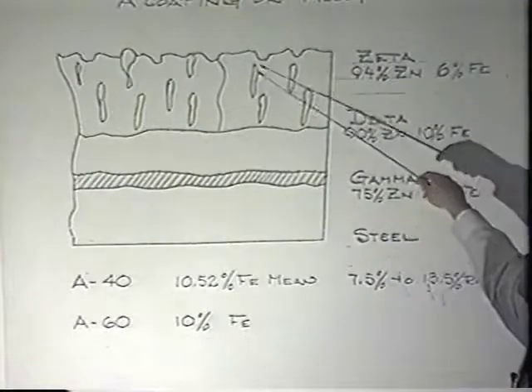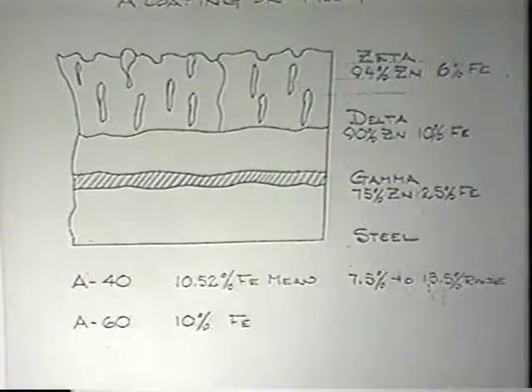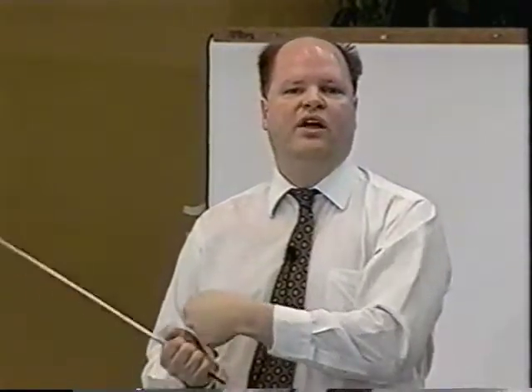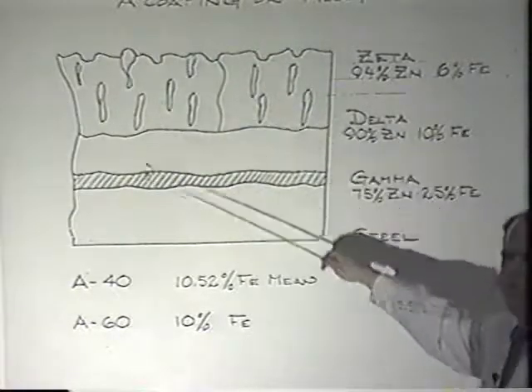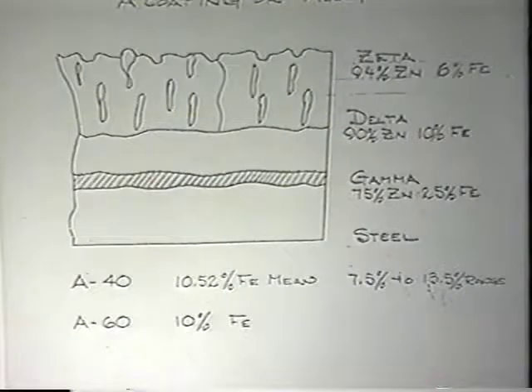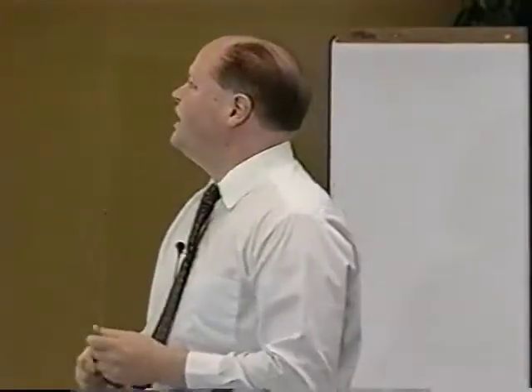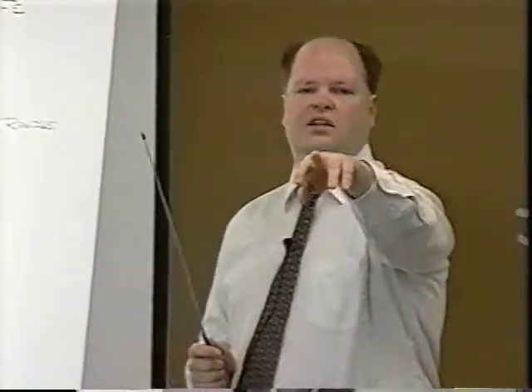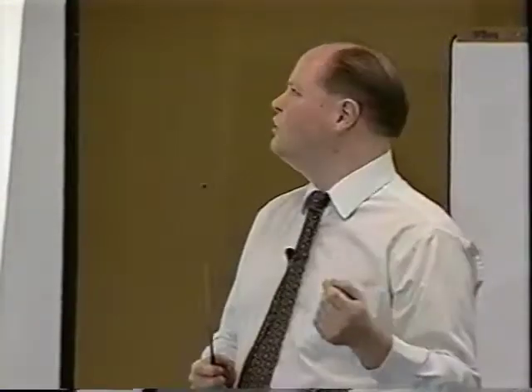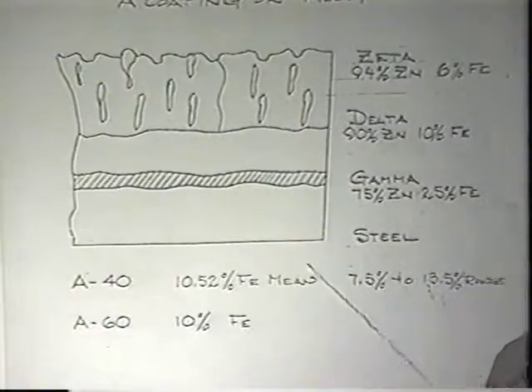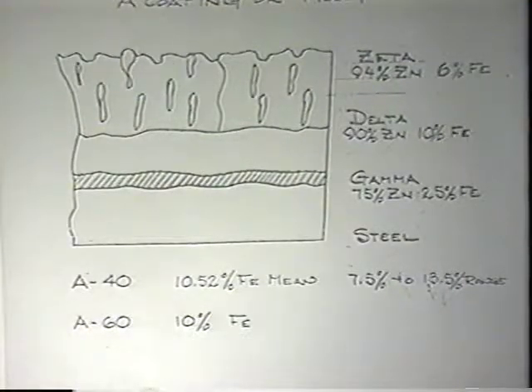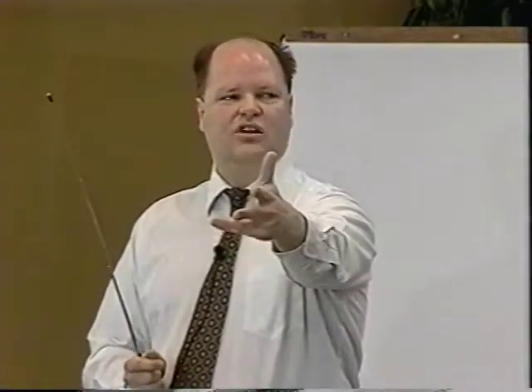Some interesting properties of this: it gives you a better weldability than the regular galvanized. In the regular galvanized, basically you've got to get through all that zinc before you can weld anything, until you get to the steel to weld. Here you already have some iron in the coating, which makes it a little bit easier to weld, so your welding tip life is extended. The other advantage is, hopefully by the time you get the galvanized ones, you'll see how smooth that is. Sometimes painting galvanized doesn't really go so well. With the galvanneal, the surface is a lot more porous, which allows the paint to stick a lot better. So you have a better paintability and a better weldability because it's getting closer to a cold rolled surface.